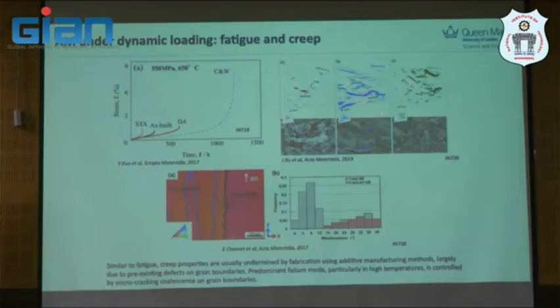And they use the, this is not atom probe, this is X-ray tomography to quantify that. And then we also do the same for our sample. But this is a cracked and uncracked sample that contributes to the creep property.